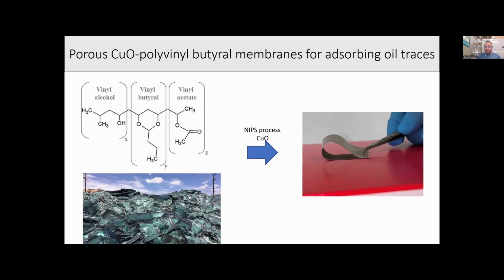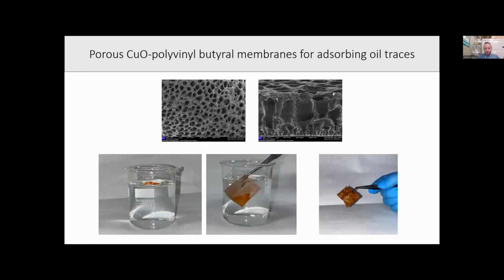A further approach concerns the use of a polymer that usually is burned. It is a synthetic polymer, not a natural polymer, that usually is recovered from windshields, so from the recycling of windshields derived from cars or from automotive industries. This polymer is polyvinyl butyral, which can be used to produce a novel kind of membrane by applying the NIPS process and by using copper oxide nanoparticles in order to improve the adsorption capacity of this novel membrane.